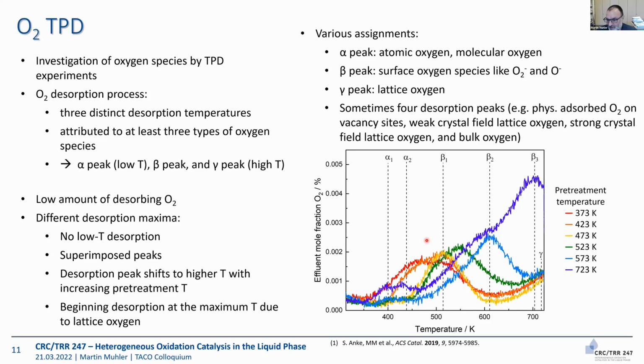What you can do is you vary the pretreatment temperature. You go up in pretreatment temperature. The more you do, the more you shift the maximum to higher temperature. You desorb more and more. But it's not really possible to clearly assign these peaks, and also the literature is quite confusing. All you do is you label them alpha, beta, gamma, but that is not really insight.